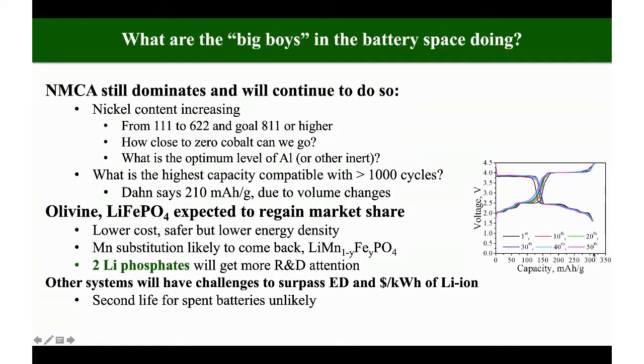And you see we get about 305 milliamp hours per gram out of this, as compared with about 200 out of the layered oxides. There are still some issues here, but you can see this is 50 cycles, and the 50th cycle is in fact better than the first. So we've got proof of principle that we can stuff 2 lithium ions into a lattice without destroying it.